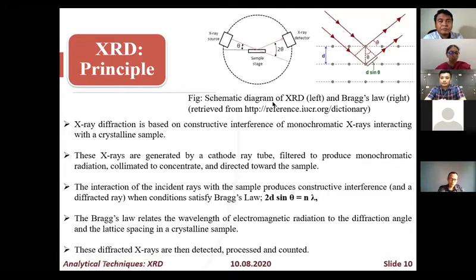The principle of XRD is very simple also, like the XRF. It's mainly X-ray diffraction based on the interference between the crystalline sample and the monochromatic X-ray. Usually in XRD, a monochromatic X-ray is generated from an X-ray source, and this X-ray interferes with the sample, and then the sample makes some X-ray diffraction. Using Bragg's law, 2d sin theta equals n lambda, we can detect and process this diffraction, and we can have information about the mineralogical phase present in our sample.